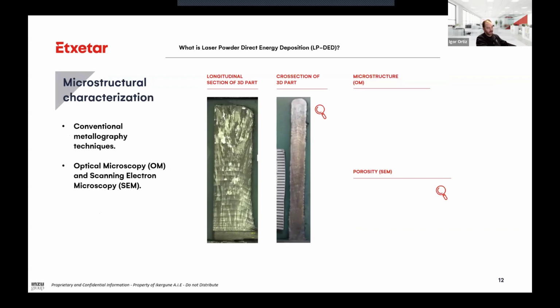In parallel or after, we also check the as built samples, just a cross section, with the optical microscope and the SEM microscope, to see if there is any crack, any lack of fusion, any cross contamination of the powder, and also the porosity, and how the behavior of the powder is with the laser parameters and all the research that we are doing.